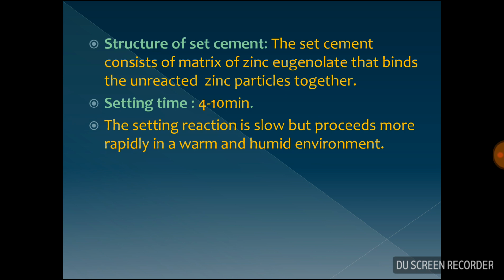Structure of set cement. The set cement consists of a matrix of zinc eugenolate that binds unreacted zinc oxide particles together. Setting time is 4 to 10 minutes. The setting reaction is slow but proceeds more rapidly in a warm and humid environment.